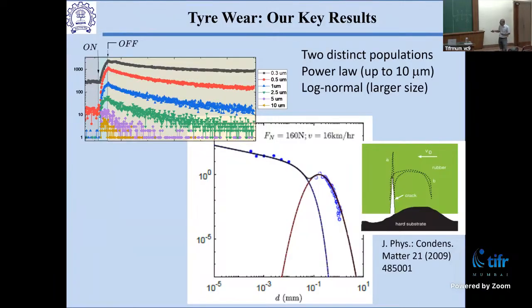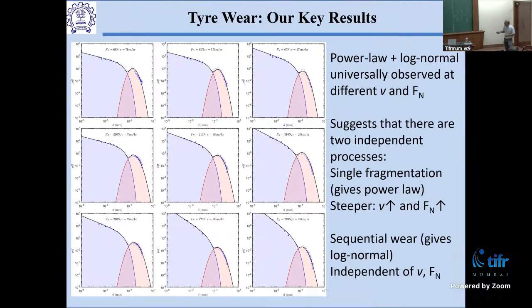Particles that are large and that settle down form this distribution, which is a log normal distribution, similar to what we saw earlier. That really just comes from the central limit theorem. You take something, you keep fragmenting it, eventually the distribution has to be log normal. And so that's what you see. This is sequential fragmentation that you get in the structure. But there's another set of particles that give you something that looks like a power law, right? And this is true as you increase the speed. It's true as you increase the weight of the particles.